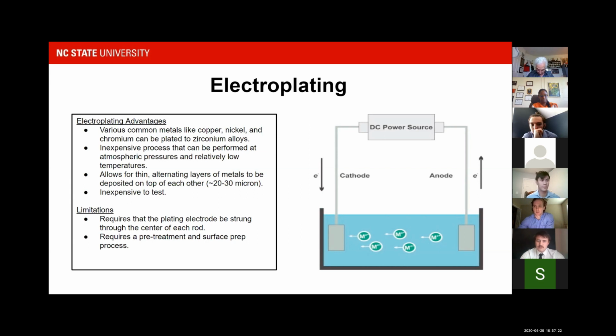So electroplating to us seemed to be the process that was the most feasible while still being able to provide a coating on the inner diameter of the zircaloy cladding that would stand up to the demands of environmental conditions in a LOCA accident. Electroplating is great because you can put a variety of different metals, chromium, nickel, copper, and it allows a very thin and a very even coating depending upon your anode geometry and how the bath is arranged. If that's done properly, then you can get a coating in the 20 to 30 micron range.